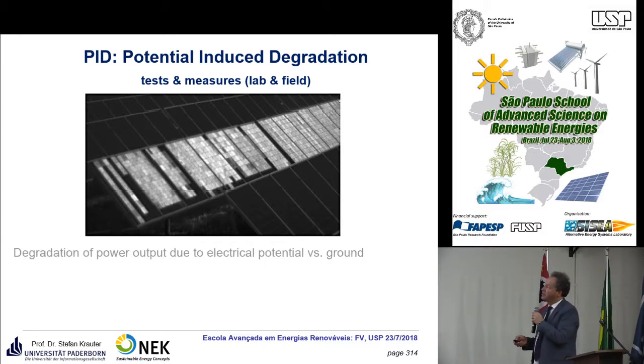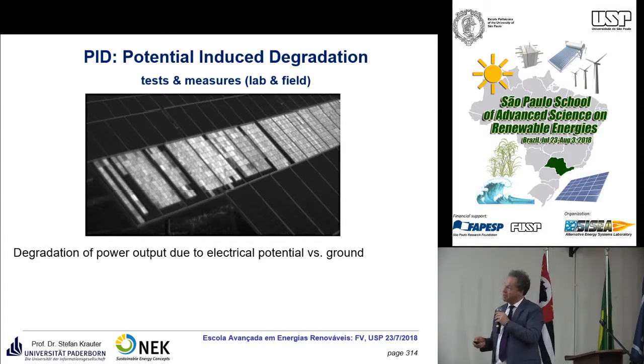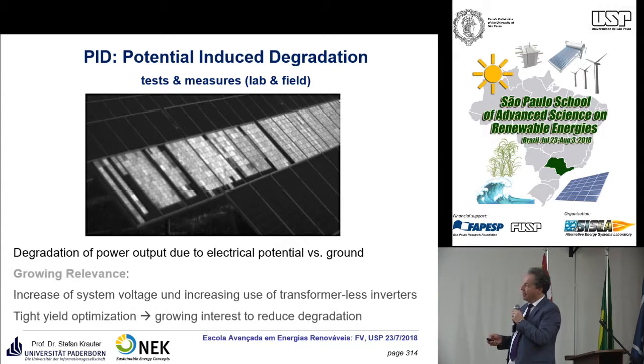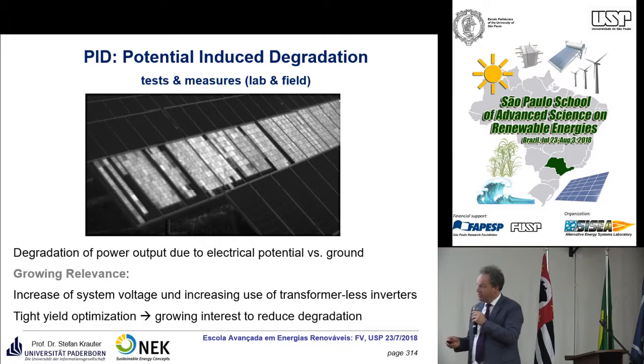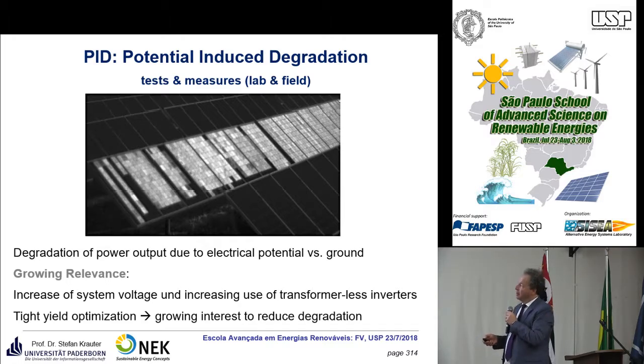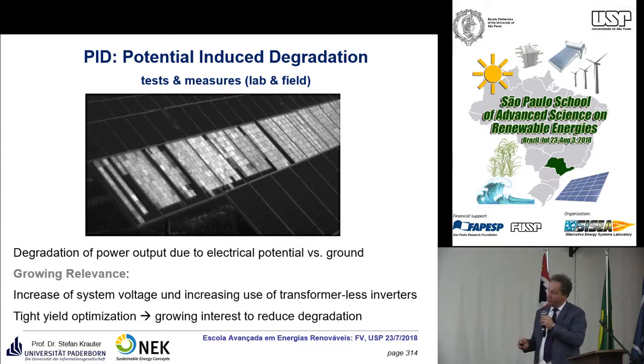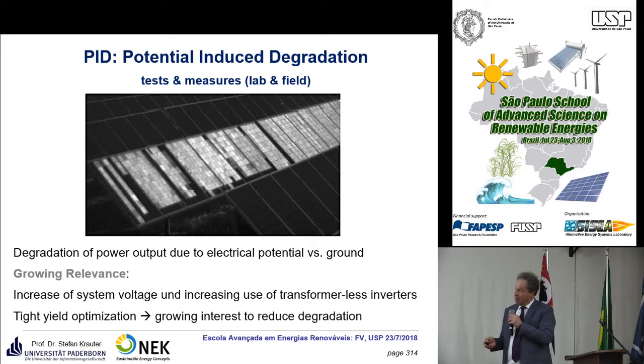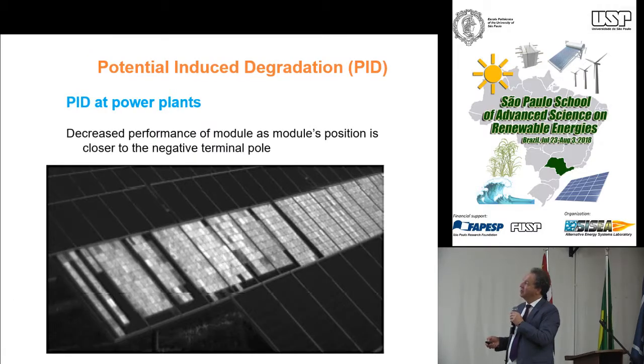This is a quite interesting effect because it depends on the electrical potential versus ground. This is due to the increase of system voltage and the increasing use of transformerless inverters. This wasn't really so relevant before because nobody cared about it, but now there is a really tight yield optimization.